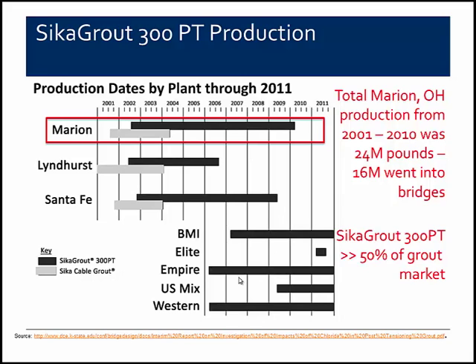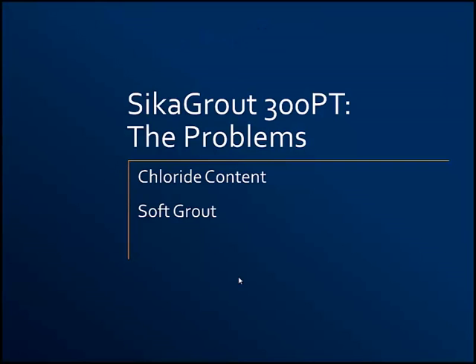During that time period they were making the grout from 2001 through about 2010. They produced about 24 million pounds of grout, roughly 16 million pounds of which went into bridges. And from discussions in the industry, it appears that during that time period Sika was the dominant grout producer in the PT market with well over 50% of the market share. So now we're going to get into some of the particular issues with the SikaGrout 300PT product, primarily the chloride content issue that you may have heard about, and then some other issues related to soft grout.